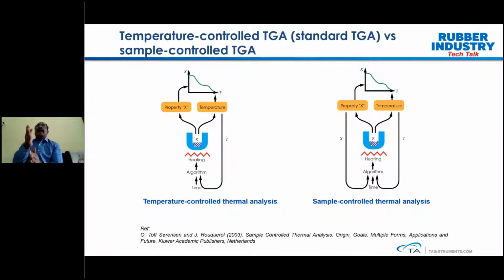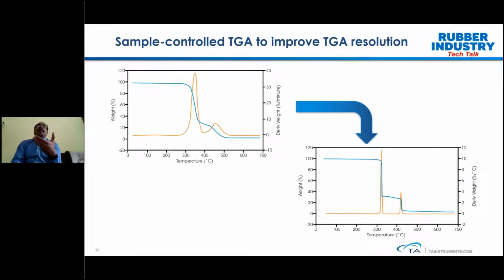This way it will have a dynamic heating rate. So depending on the pattern of how the sample is going to decompose, the control mechanism or the associated heating rate also is going to change, and that we call dynamic heating rate, high resolution TG. So what is the improvement you are getting? You are able to resolve those decomposition patterns in a better way. So that's one of the key advantages.